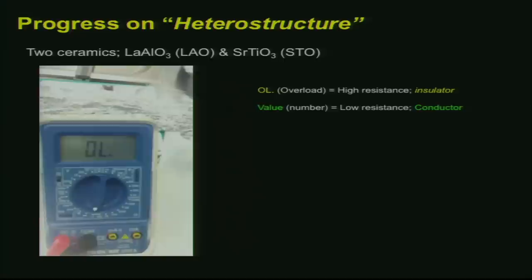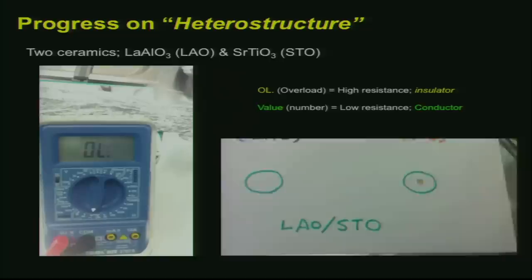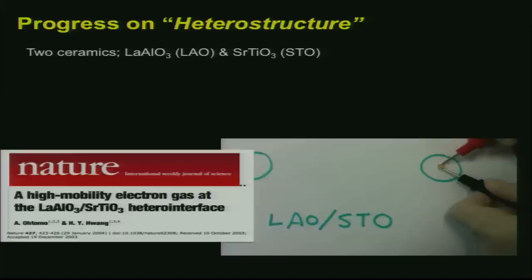Then what happened? If you make a sandwich like that, move it to here. Then people found conducting behavior in the material. I cannot show that, but a professor at Stanford University found conductivity when they made a sandwich, LAO/STO. This is awesome, because as I showed, these are two completely insulating materials. However, when they are attached together, they start to show conductivity. It's kind of metallic behavior.